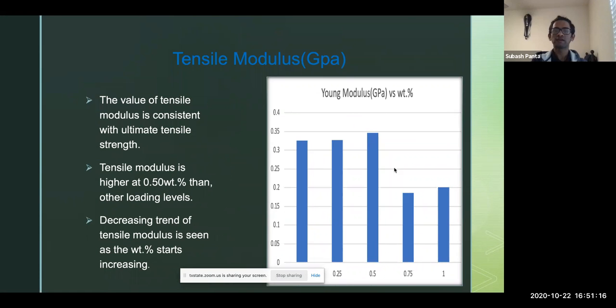Tensile modulus. The value of tensile modulus is consistent with ultimate tensile strength. Tensile modulus is higher at 0.50 weight percentage than other loading levels. Decreasing trend of tensile modulus is seen as the weight percent starts increasing. So at 0.50, we can see the tensile modulus is higher than all other weight percentages. So 0.50 is higher, and at 0.75 and 1% the tensile modulus is low. That's because all the alumina nanofiber is agglomerating in the resin.